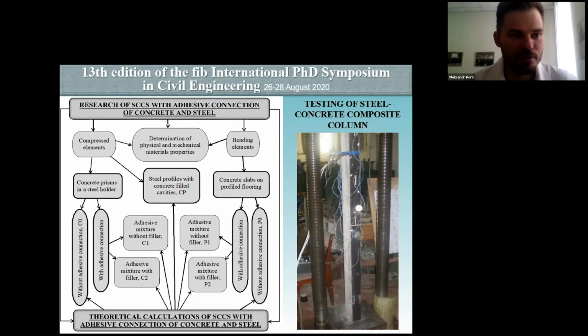But we add third, one more type of material. It's polymer. And it was difficult to take into account work of this material when it's staying between steel and concrete. And it's a very difficult calculation step. And we now try to fight this problem on this stage when we have very thick layer of polymer. You can see on photo column, double T column with cavities filled with concrete. And in this way, liquid concrete was glued, was adhesive to steel part.